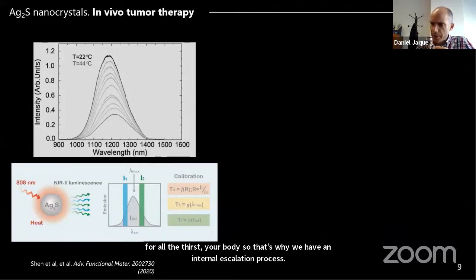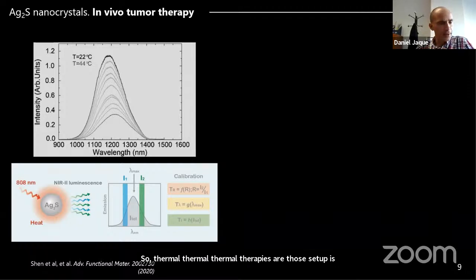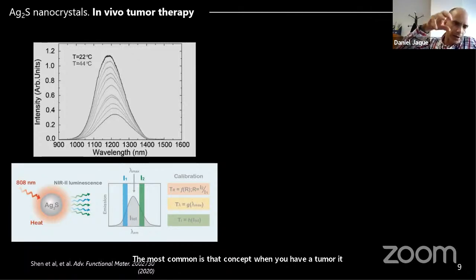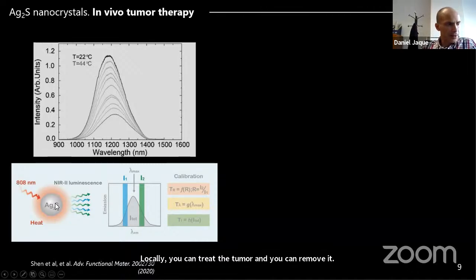So thermal therapies are those therapies based on increasing the temperature of the tissues to treat some disease or some problems. The most common is cancer. When you have a tumor, if you are able to heat the tumor locally, you can treat the tumor and you can remove it. In this work, when you excite the silver sulfide nanoparticles, these nanoparticles produce luminescence, and also produce heat. Luminescence is strongly dependent on temperature, and you have different parameters to measure the temperature. You can measure by the position, or by the ratio between two bands, or by the intensity. The important thing is that you have a nanoparticle that is heating and is also emitting light that can be used for thermal reading.